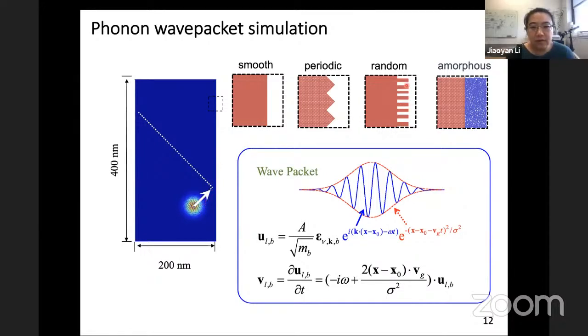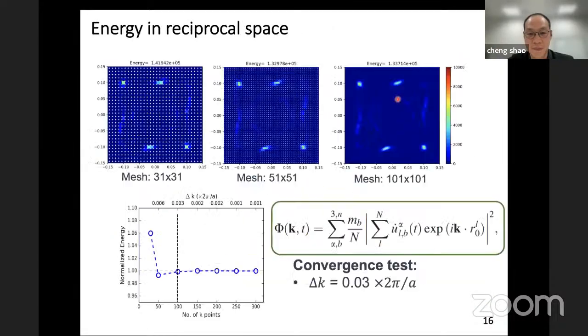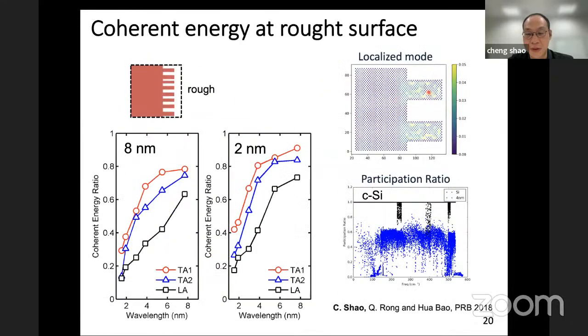I see. And then actually the large structure or the boundary will only affect around 3 nanometers near the interface, and in the other regions, the dynamics are very similar to the bulk system. Okay, I see. So no matter how big your sample is, you just analyze the eigenmodes for the supercell. Okay. Yeah. And that means this method is limited to crystal material, right? So if you have some kind of amorphous phase, it might be hard to. Okay, got it. Yeah, thank you very much.